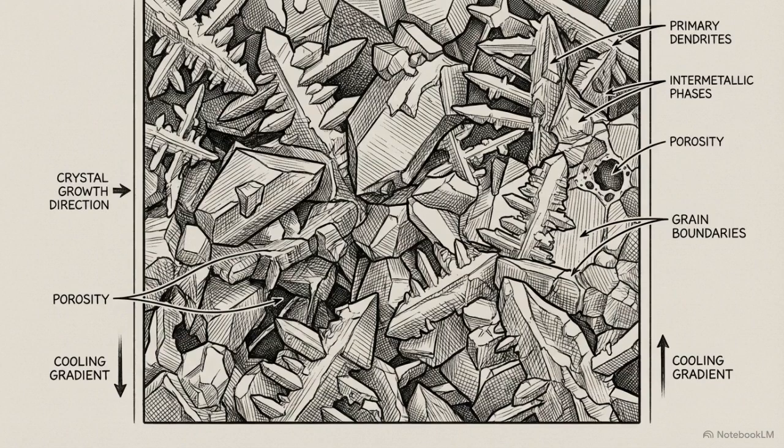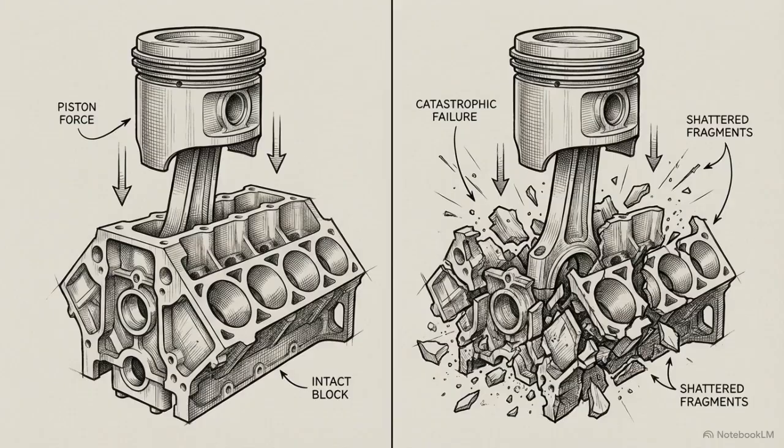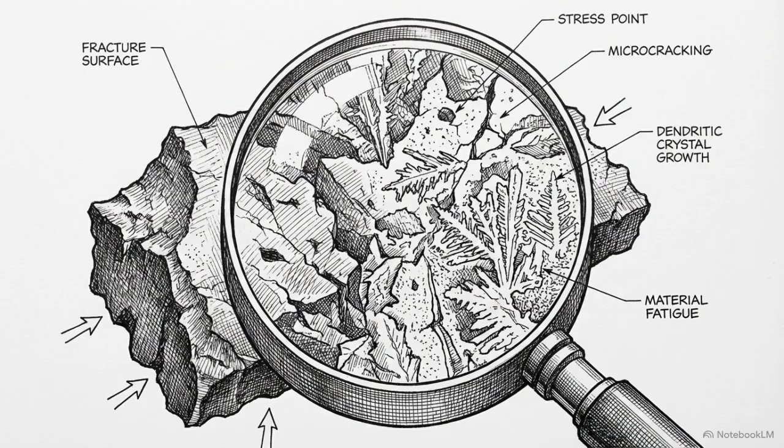The speed of the cooling process creates extreme thermal gradients, resulting in a chaotic, highly stressed microscopic architecture inside the metal. The mechanical integrity of an HPDC component, whether it holds pressure or shatters under load, is dictated by this non-equilibrium microscopic architecture, rather than its bulk exterior shape.